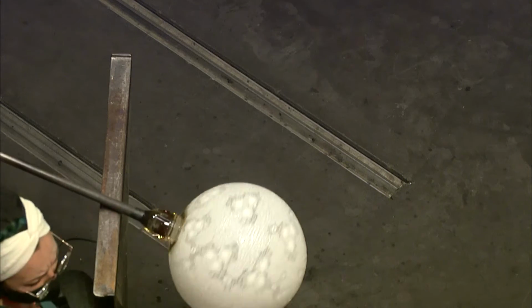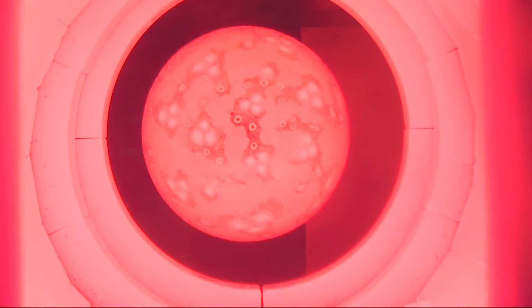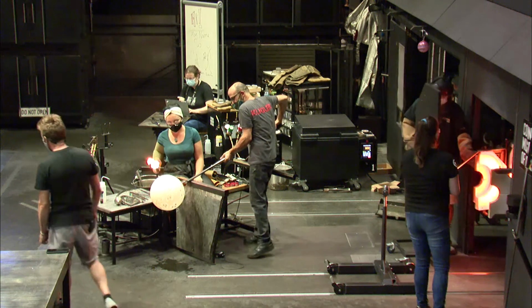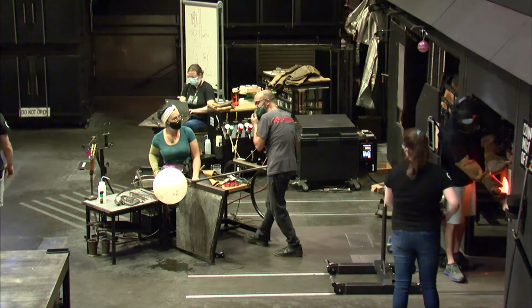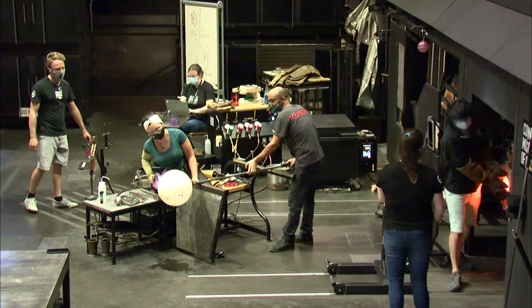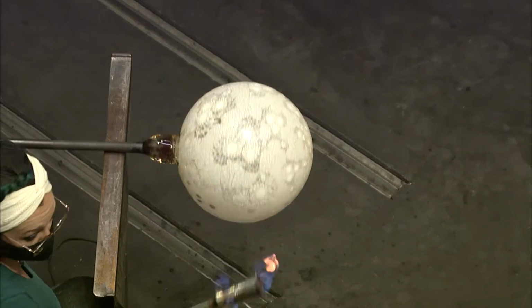Yep. And a flash is just that very brief reheat, just a maintenance heat. Make sure the temperatures are where they need to be. Learning those temperatures, that's something that also comes with experience. Obviously, we're not looking at it with our eyes and telling you exactly how hot it is. But the annealing does start at 900 degrees for this type of glass. So that's where our annealers are set. And they are programmed, when we start the program, to slowly cool down over whatever time we need it to. And this, again, probably 12 hours.